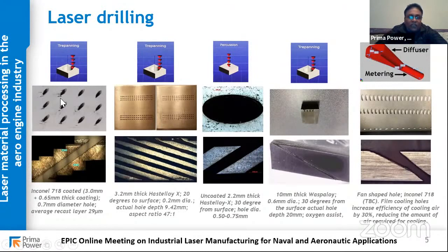Most of the holes are actually done at an angle. It's very rare that you drill at 90 degrees; most are 30 degrees from the surface. This is an example of drilling through a TBC. If you look at the top, this is the top of the hole, and this is a cross section. When you're drilling a hole, the one thing you need to look for is that there's no cracking in the parent material and no cracking in the recast. Recast is the material which solidifies along the length of the hole. So this is an example of TBC.